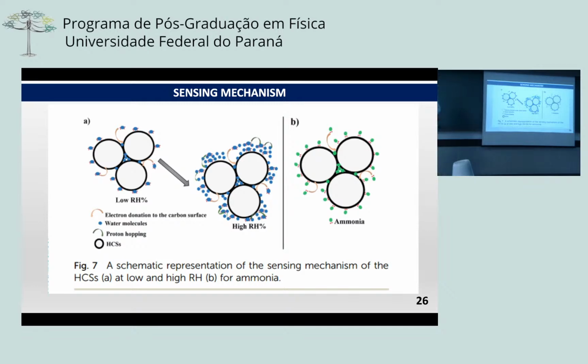We considered a hollow pore filling in that when water gets into the pores or adsorbs onto the pores, water has got higher electronic conductivity than air, and therefore the lone pair of electrons in the water will interact with the carbon, creating a dipole charge, further leading to an increase in conductance. And at very high relative humidities, because of the high dipole moment of water, you then have proton hopping taking place, and therefore you experience very high conductance. In the case of ammonia, the same principle applies. Ammonia is more conductive than air, and therefore when ammonia molecules get into the pores, they are able to create a dipole charge, further leading to a change in conductance, which is way different from the mechanism for carbon nanotubes and graphene, which are highly sp2 hybridized.